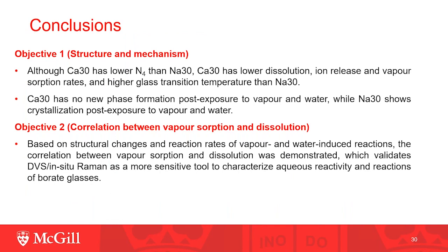Therefore, based on the experimental results, we conclude concisely that although calcium-30 has lower N4 than the sodium-30, calcium-30 has a lower dissolution ion release and vapor sorption rate and a higher glass transition temperature than the sodium-30. Secondly, calcium-30 has no new phase formation post-exposure to vapor and water, while sodium-30 shows crystallization post-exposure to vapor and water.